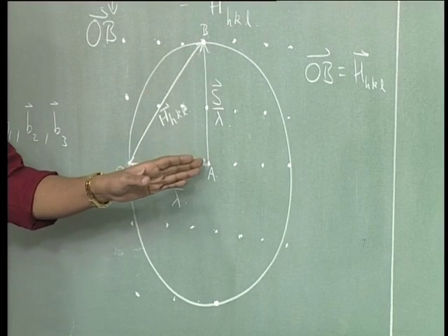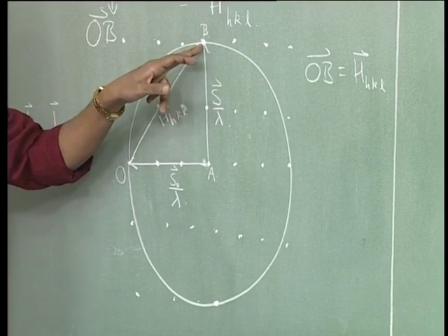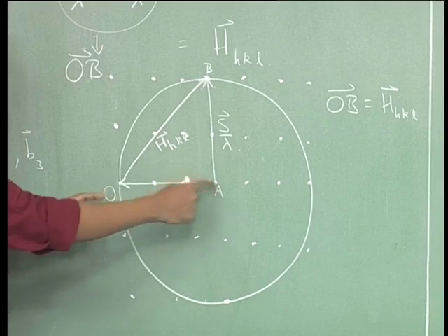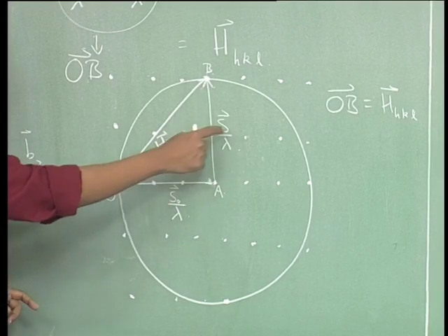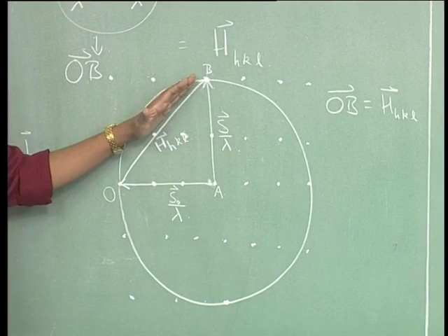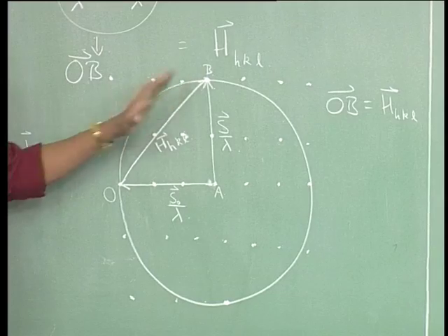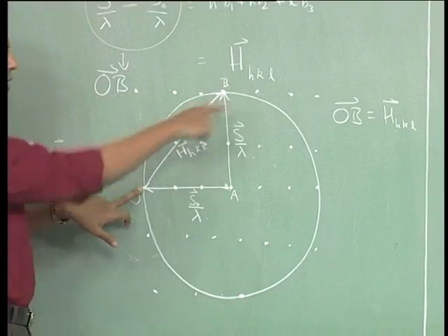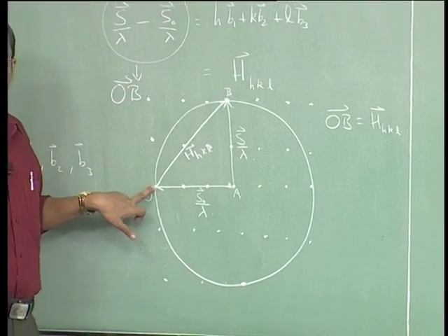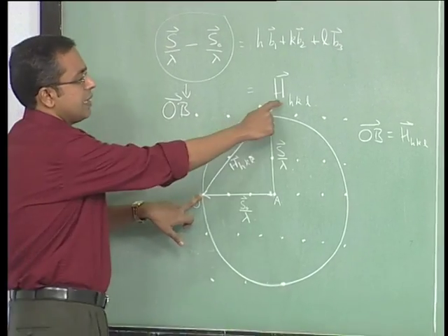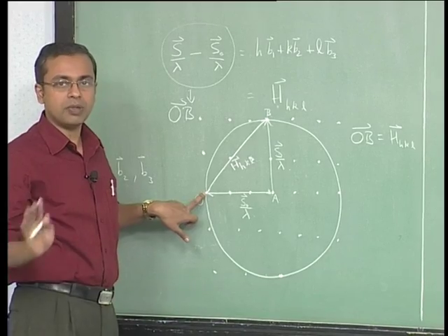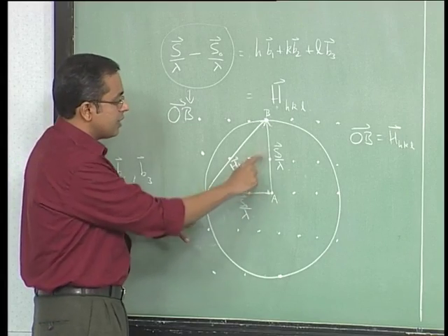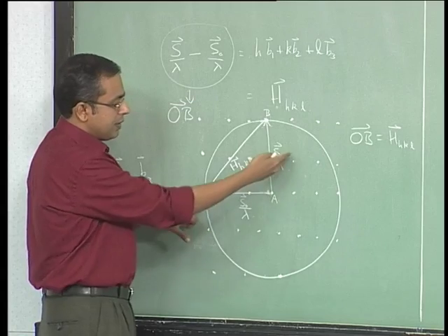as so at that point you not only have the correct magnitude of wavelength, which is 1 by lambda, but you also have a direction such that the difference between the incident beam vector and the diffracted beam vector is a valid reciprocal lattice vector. Any valid reciprocal lattice point, if you connect the origin to it, gives you a valid reciprocal lattice vector which is designated by HKL. Anytime the circle also touches that point, then the circle is being defined by the difference between these two vectors.